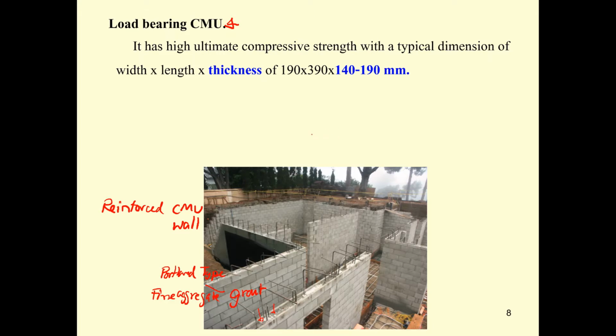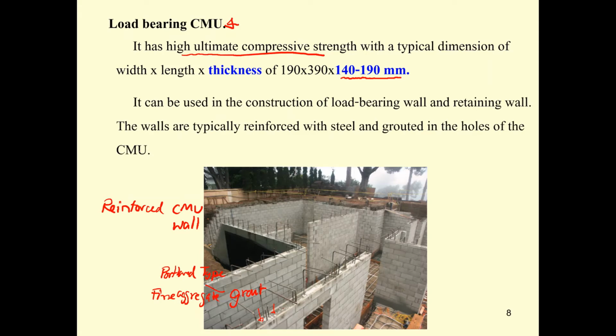And the load-bearing CMU usually has a thickness between 140 to 190 millimeter, and it has high compressive strength. Okay, and it's also a severe weathering grade. Based upon this, this load-bearing CMU can be used in the construction of the load-bearing wall, as I mentioned, and also the retaining wall. A retaining wall is a kind of wall that resists the pressure from the soil. That means this kind of wall will contact with the soil and water. So the grade of the CMU unit that we are going to use is the severe weather grade.